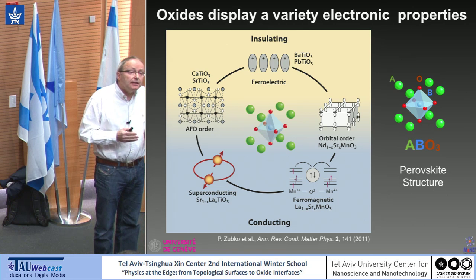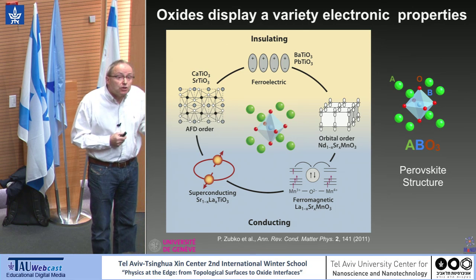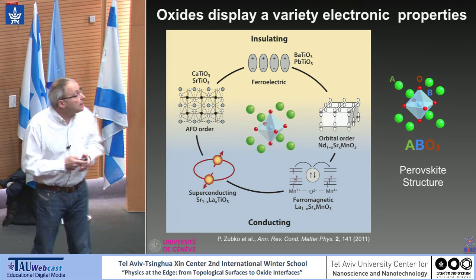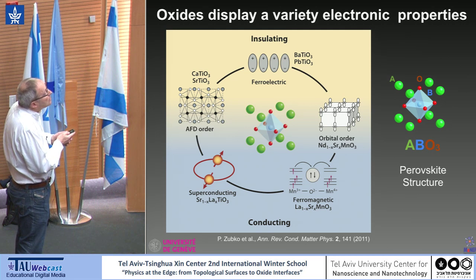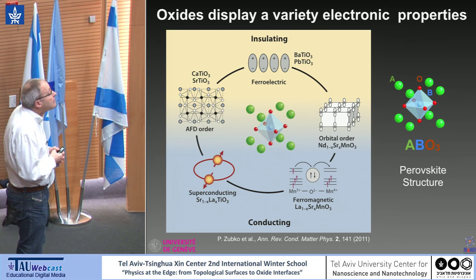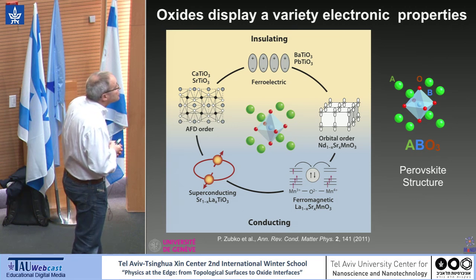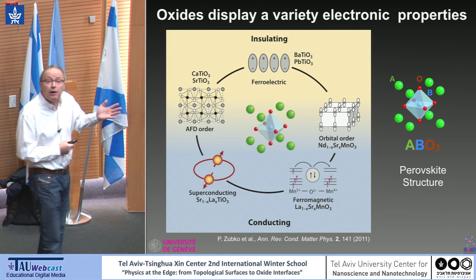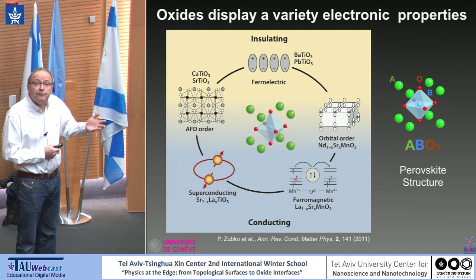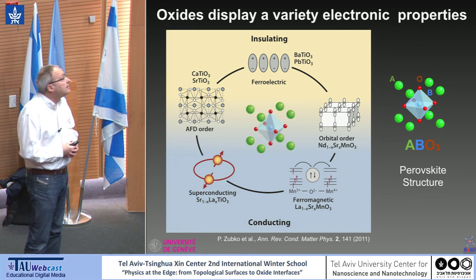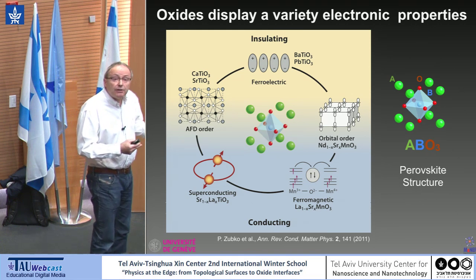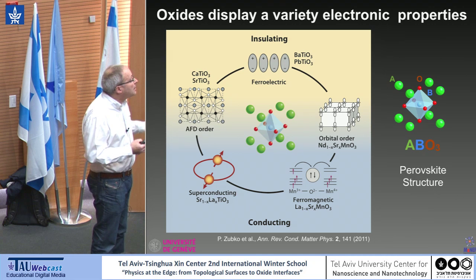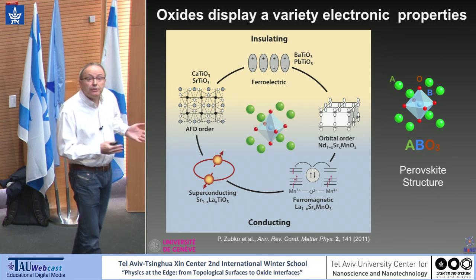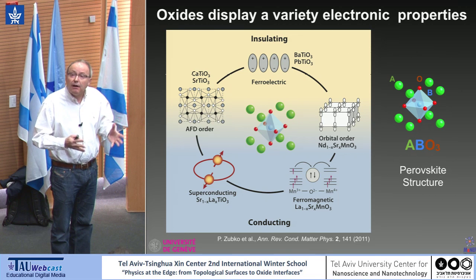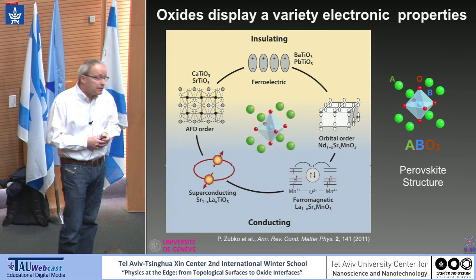a variety of instabilities. Some of these instabilities are structural. They can be antiferrodistortions, like here, rotations of oxygen octahedra that you find at low temperature, for instance, in strontium titanate. You have polar instabilities, which lead to ferroelectricity. This is what you find in barium titanate. And you can have electronic instabilities leading to orbital order, magnetism, or superconductivity. And all these properties are found within the same family of materials.